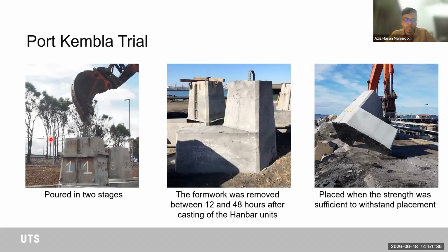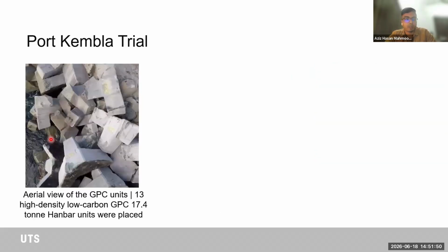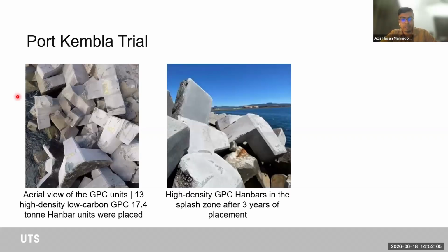What we mean is, we collected some samples and took them back to the lab, and we were monitoring the strength development of these concrete cylinders. And when we achieved target strength, we could move around these units and place them onto the breakwater. Here's an aerial view of the geopolymer concrete units. So we made 13 high density, low carbon geopolymer concrete armor units, each with about 17.4 ton in weight.